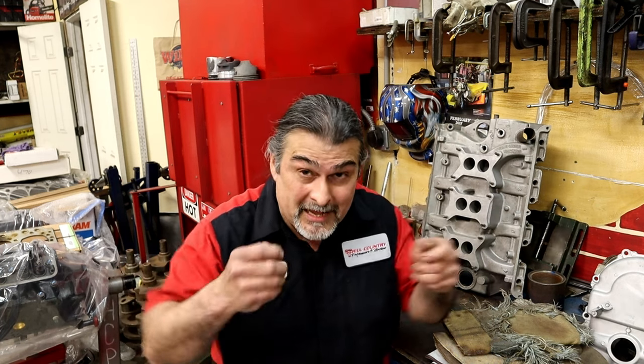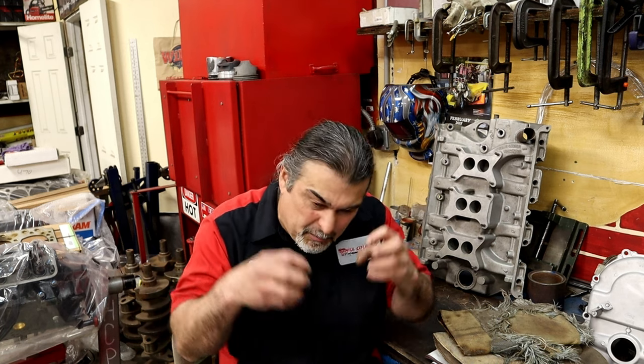1 out of 10. Then I learned, wow, I'm having to really crank down on it. I brought my barbecue pit from the house, propane, fired up, put the Escort head in there, cranked it up as hot as I could, opened the barbecue pit, and welded in the barbecue pit. Man, that was my biggest key. I was like, wow, preheat the head. Preheating the head, you're not cranking down on it and just burning the aluminum. Also, a big, big part, preheating the head is going to keep that head from distorting.